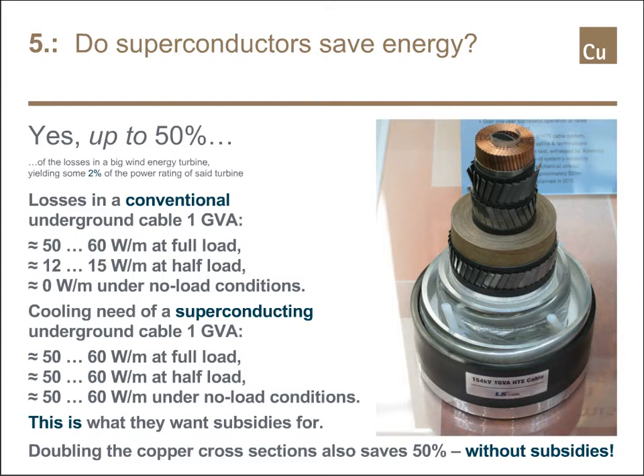And they also try to promote superconducting high voltage and extra high voltage cables. And I always wondered how much energy you need to cool them down permanently to 100 Kelvin, 90 Kelvin, 80 Kelvin, which are their operating temperatures. And it took me years to find out finally that it was about 50 to 60 watts per meter which you need. Now, I calculated the losses in a conventional cable, and I ended up with something around 50 to 60 watt per meter at full load.